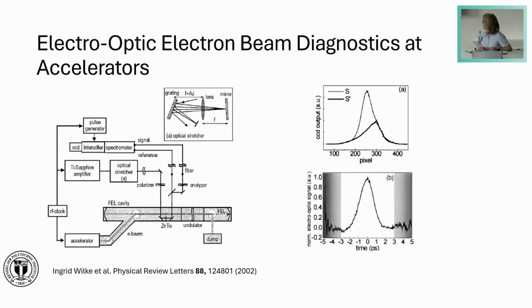The actual experiment was almost 25 years ago at the University of Hamburg, when I was working on my habilitation in experimental physics. The experiments were performed at the FELIX free-electron laser in the Netherlands. The free-electron laser is driven by a linear accelerated electron beam, and we put a zinc telluride bulk crystal in the beam pipe in the vicinity of the electron beam. Now if the electron beam travels past the crystal, it changes the optical properties of the material, and those changes are probed with the laser beam.